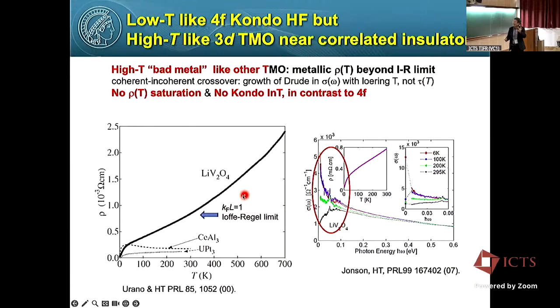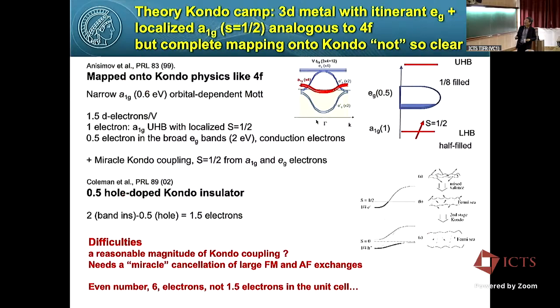And this is in marked contrast with 4f heavy fermion systems, like cerium and uranium compounds. They do show a kind of saturation around 100 microohm centimeter. And of course, often they show Kondo logarithm, but we don't see that. So in that sense, it looks like a really bad metal behavior of a correlated transition metal oxide, like the cuprates and ruthenates.